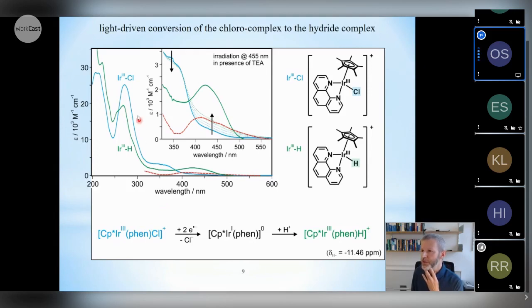You see here UV-Vis spectra in green, notably the iridium hydride complex, which has this metal-to-ligand charge transfer absorption band around 430 nanometers, which is not there in the blue iridium chloro complex, or at least not as pronounced in the beginning. But as you irradiate the solution here in the presence of triethylamine, you start to see how this band is growing in here. And at the same time, in proton NMR spectroscopy, you begin to see the hydride resonance.